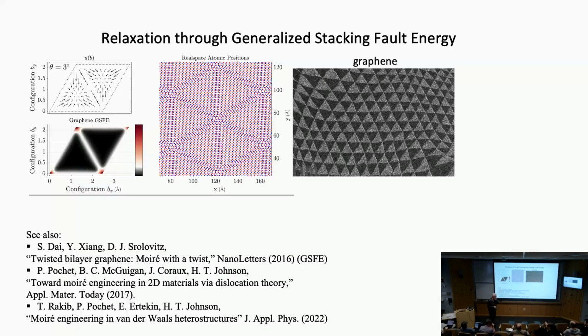Yes? Because the moiré twist is not the global minimum, right? Correct. So how do you go to a local minimum but prevent your code from going to the global AB stack minimum? First of all, we don't do the relaxation on the full moiré; the energy landscape is for a single atomic unit cell. I went too fast on that. You don't need the full moiré, you just need the two-atom unit cell of graphene in each layer. I'll show you later actual calculations with the full unit cell with 13,000 atoms. And the way that you don't go back is because you have a relative twist to begin with. So the whole lattice cannot untwist because that would cost a huge amount of energy. I don't know if that makes sense.